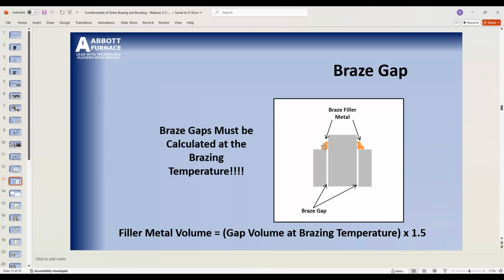The way we calculate how much filler metal to put on is we calculate the volume of the gap. If I had a piece sitting down inside of a sleeve, I would calculate this gap, but I have to calculate it at the brazing temperature. So if we're going to braze at 2050, take into account the expansion of all the components. That gap's going to be bigger than it is at room temperature. Calculate the volume of that gap, and then add about 50%, 1.5 times, and that will ensure that you have enough filler metal to flow in and give you a good bond.